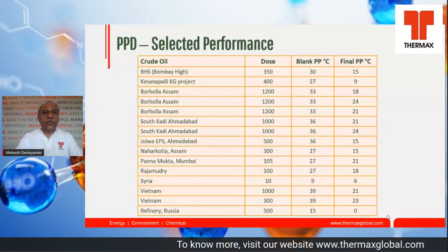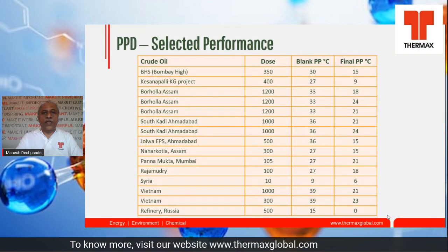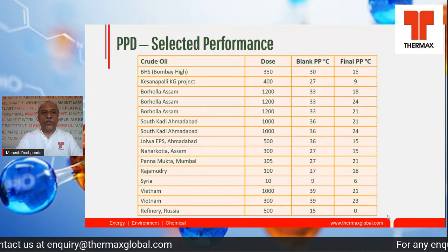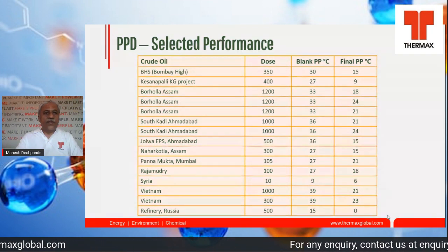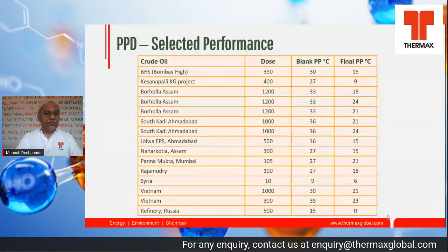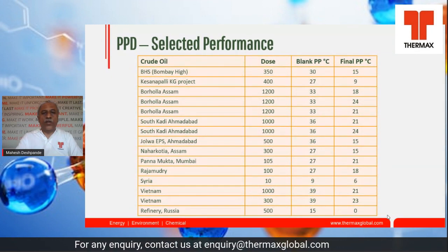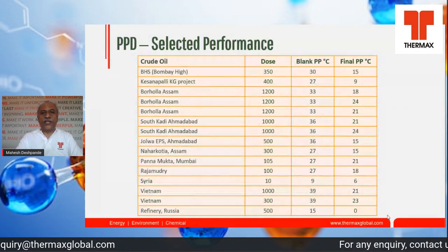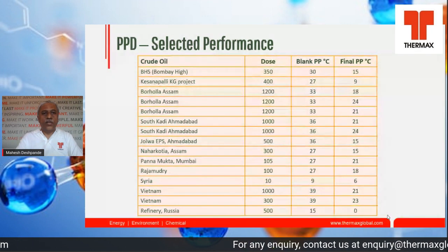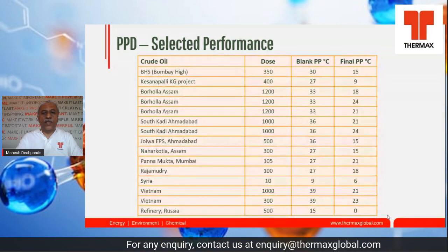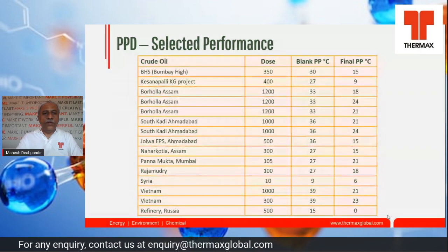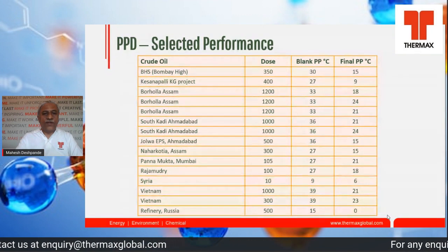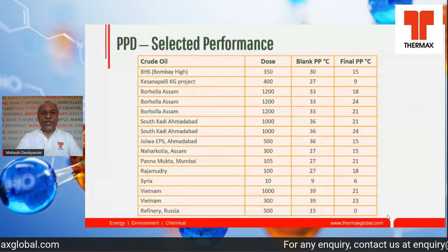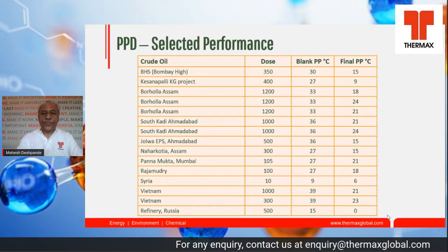In Kesanapalli crude in Krishna Godavari district at 400 ppm, it reduced the blank pour point from 27 to 9 degree. Then there are some examples of Assam, different varieties, in Borholla crude. Again, because of wax nature, the dosage is higher and the reduction is lower as compared to earlier oils. It all depends upon the wax percentage, wax molecular weight. So below you can see different varieties and different depressions achieved at different dosages.